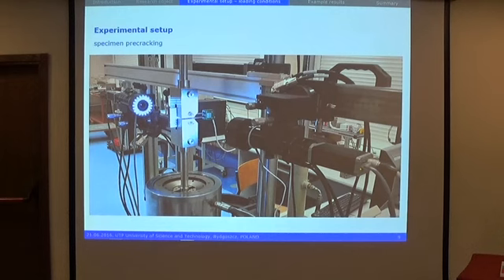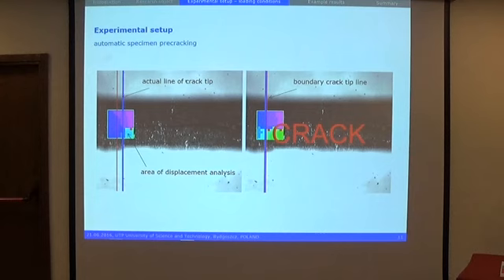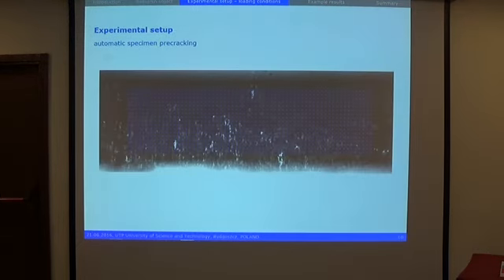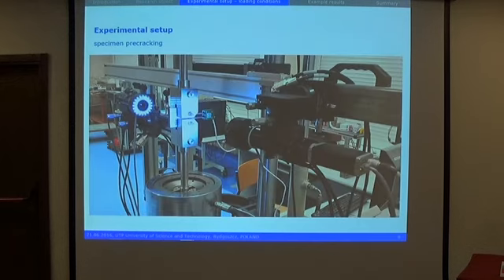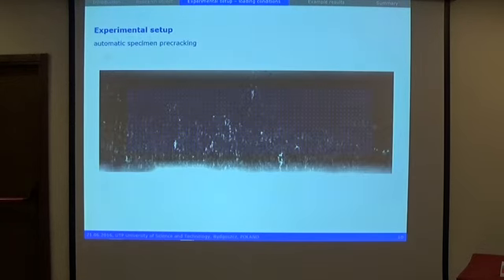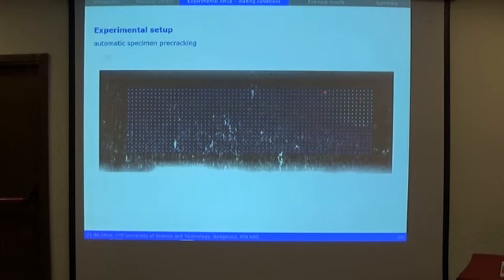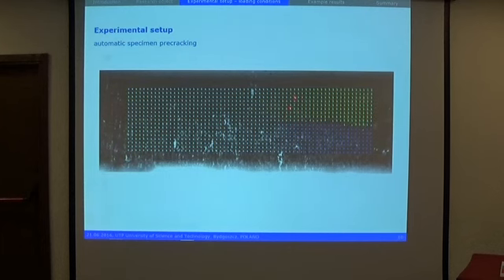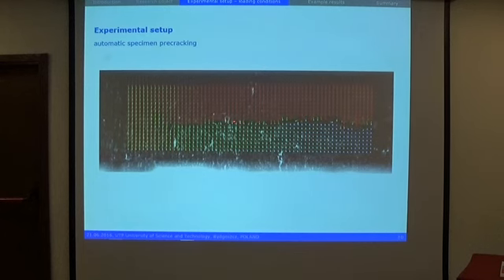During the test, one moment, it should be a short movie. Okay. During the test, the displacements of the points around the crack were calculated, and on the basis of gradient analysis, the actual position of the crack end was determined.